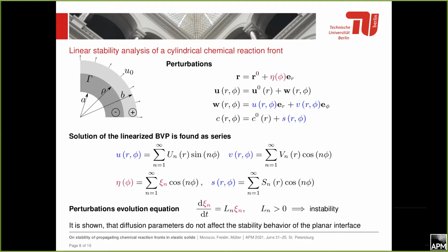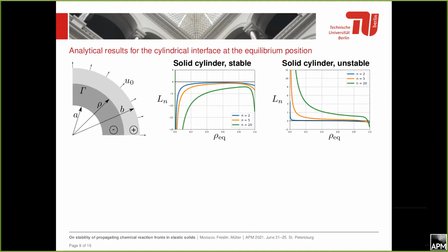By the way, I should note that this kind of analysis was also performed for a planar interface problem, and for that case it was possible to show analytically that the diffusion properties of the material do not influence the stability behavior. In other words, only mechanical properties define whether the reaction is prone to be stable or not. And having said this, we want to analyze our Lns in terms of whether they are positive or negative.